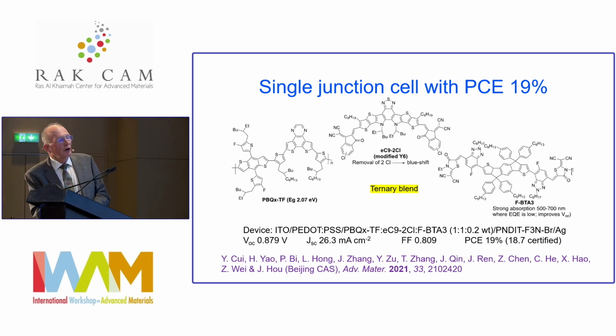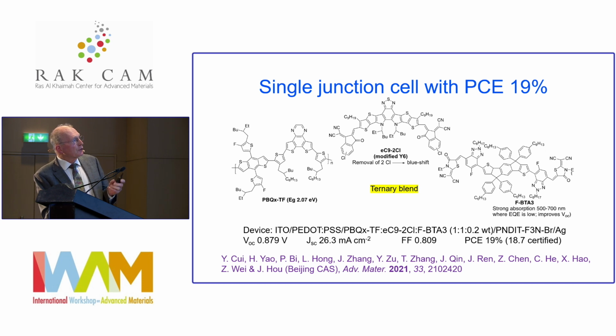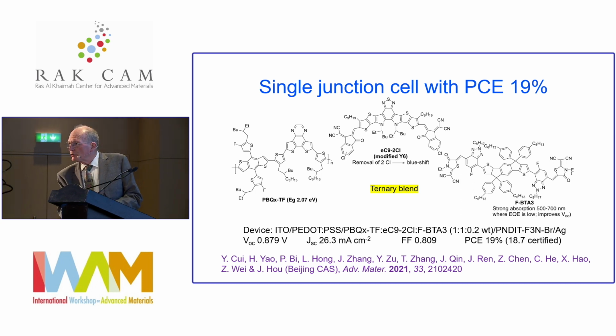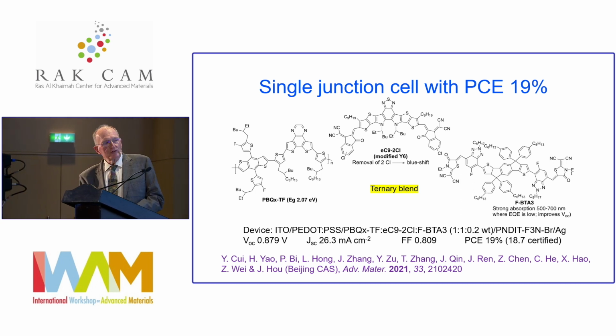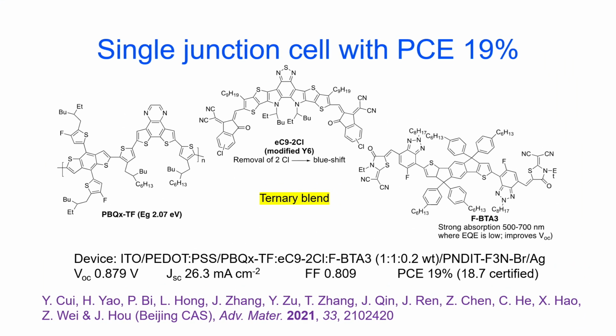And here's another ternary blend story where the donors are still very similar to the privileged donors on the left. The main acceptor is this one in the middle, which is a modification of the Y6 molecule. And then there is a contribution of this related acceptor, which is structurally different, in which the absorption wavelength in the 500 to 700 nanometer region contributes to the power efficiency of the device by being able to harness photons that aren't absorbed by the blend on the left.